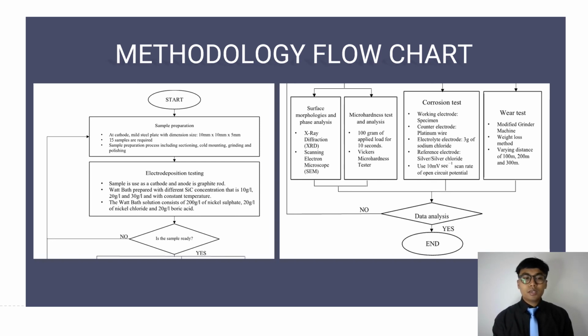And last, we do the wear analysis. The modified grinder and polishing machine was used to run the test over distances of 100, 200 and 300 meters. The sample is affixed to the machine holder before testing with a force of 20 Newton. Both the wear track and the pump that supplies the silicon carbide slurry run at a speed of 200 rpm. 3 grams of silicon carbide powder were combined with 1 liter of distilled water to create the slurry, which was then extensively agitated using a hot plate and magnetic stirrer.